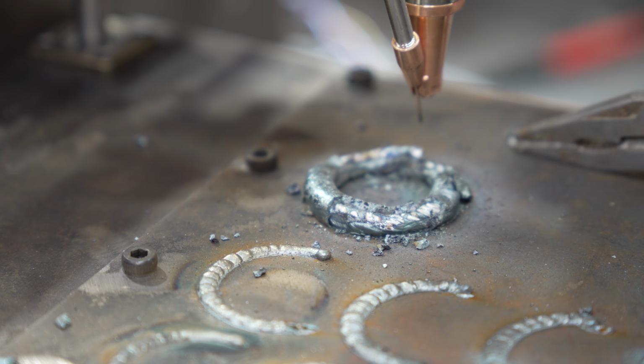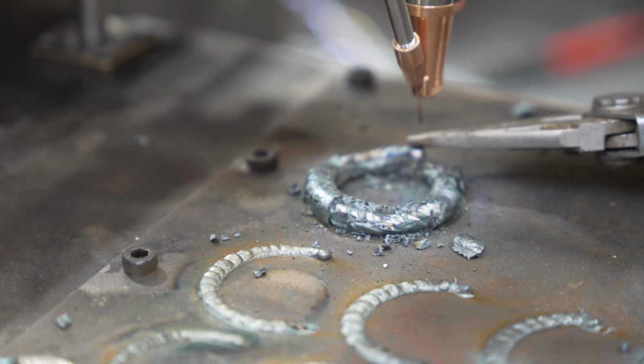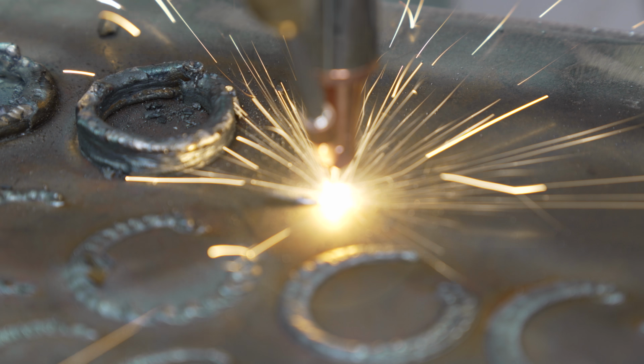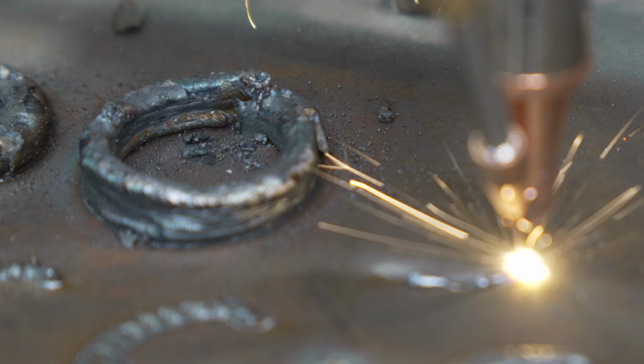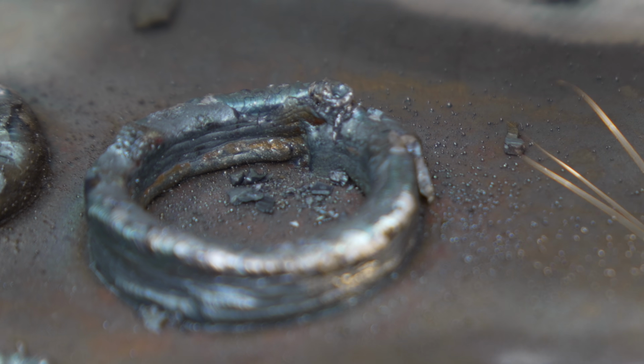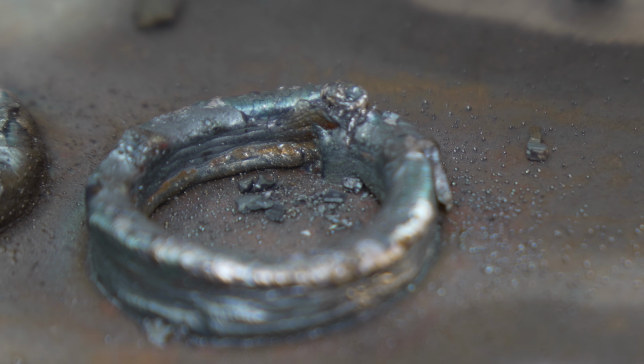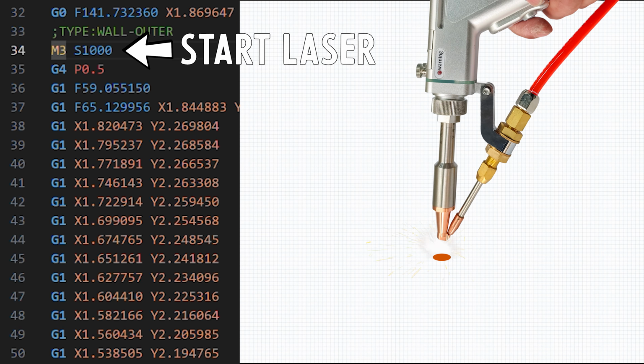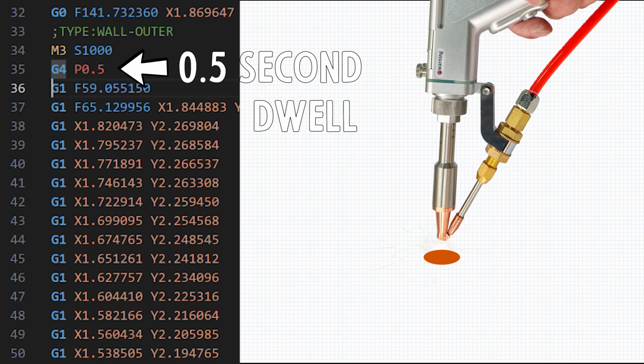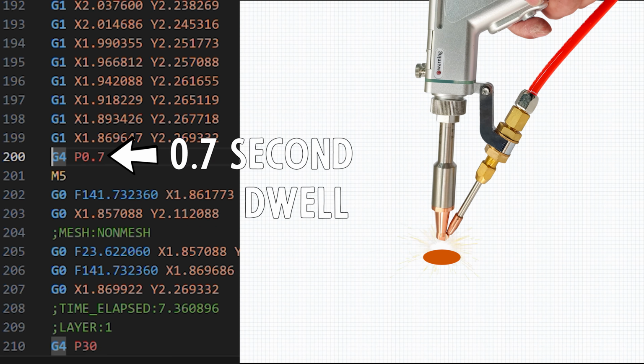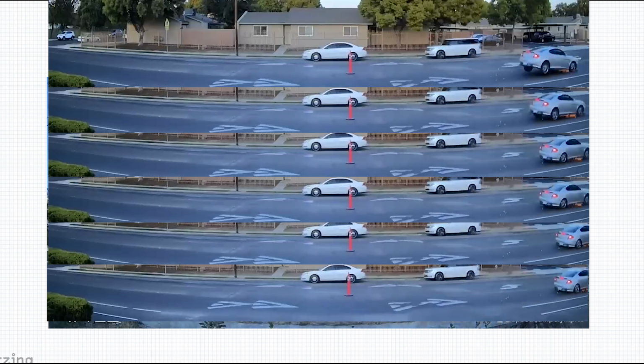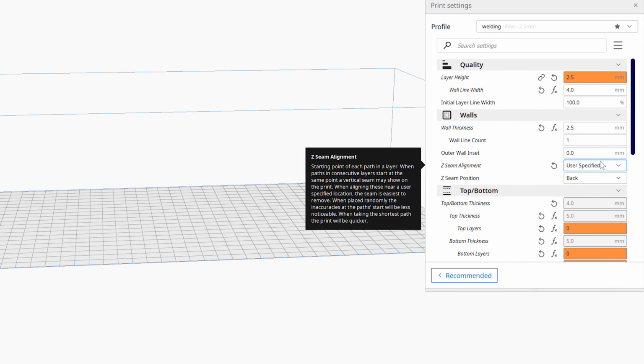The other issue, there is a height difference between the layer start and the layer end. You can really see this difference in this shot that is conveniently focused on the wrong spot. This is caused by a few things. The machine is set to pause at the start of the layer to form a puddle, and at the end of the layer to allow the wire to recede from the puddle. This can definitely cause a little bit of a bump, but the real problem is when that bump compounds over a bunch of layers. We can mitigate this problem by randomizing where each layer starts.